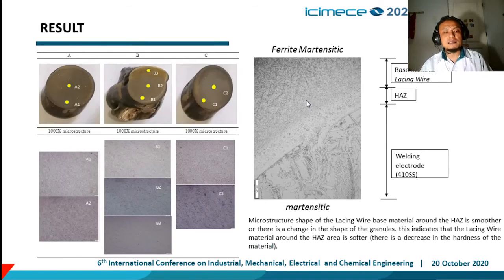So this is another microstructure image. We can see ferrite and martensite in the base metal and martensite in the weld metal. The microstructure shape of the lacing wire base metal around the heat affected zone is smoother, or there is a change in the shape of the grains. This indicates that the lacing wire material around the heat affected zone area is softer. We can check by hardness test.